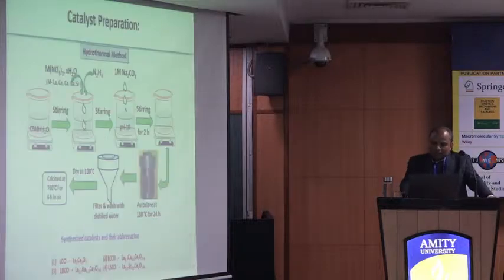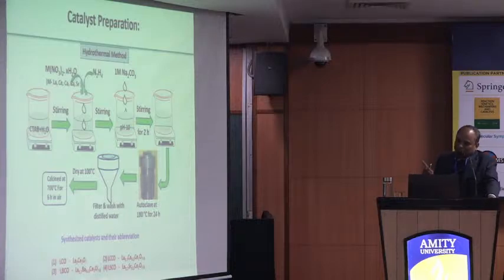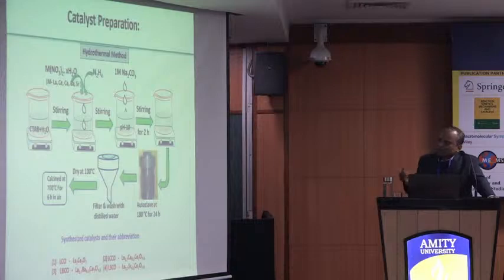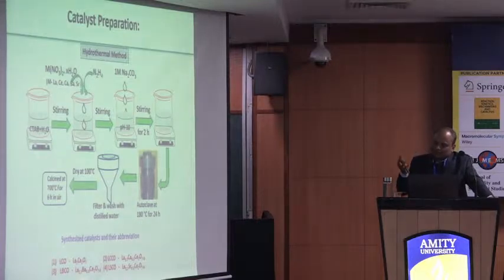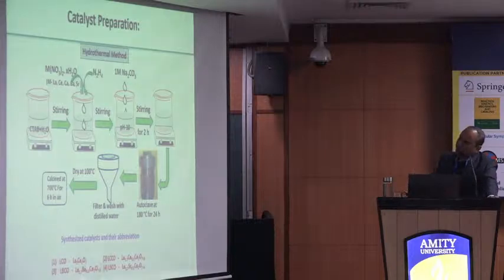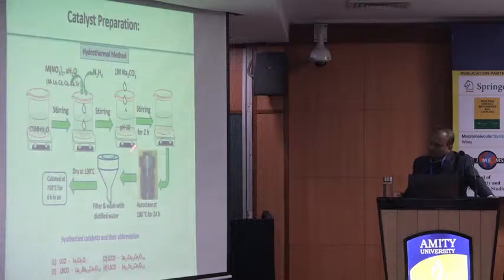We have found that calcium supported lanthanum cerium oxide is showing very high activity for this reaction. This is the preparation method. Normally we use the hydrothermal method where we use nitrate precursors for all the cases, and we did this synthesis at 180 degrees centigrade and kept it in the oven for 24 hours.